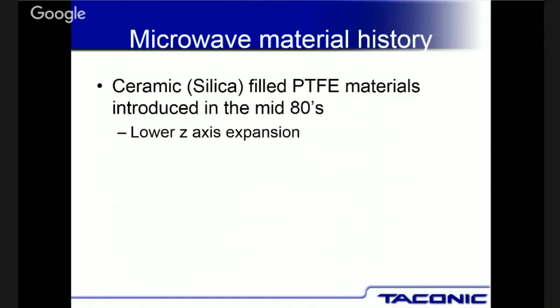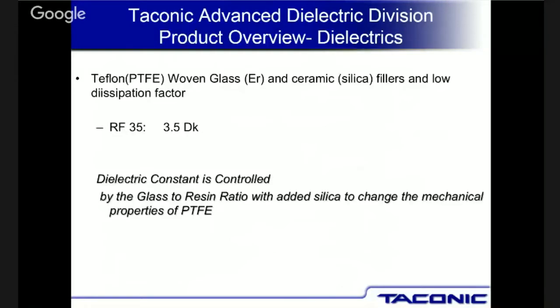So we're taking the silica, mixing it with the Teflon, and then coating that onto the glass fabrics that we then use to make the board. And that lowered the X, Y, and Z expansions in the material and made it more attractive. You could do plated through holes much easier and not have to worry about high temperature exposure in the materials and what it's going to do on making the material move or making the holes less reliable. So I think you just mentioned, George, that you use a lot of the RF35, which you've used a lot on power amplifiers that you guys are making.